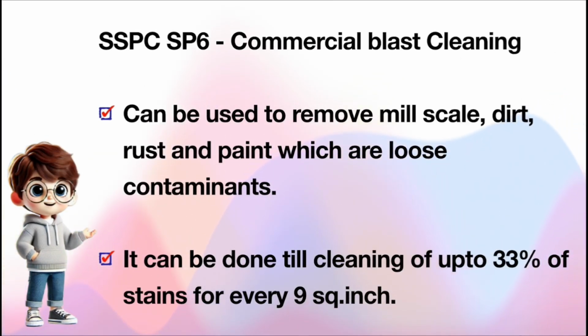Next, SSPC SP6, commercial blast cleaning. It can be used to remove mill scale, dirt, rust and paint which are loose contaminants. It prepares a steel surface by removing contaminants like oil, grease and rust, allowing up to 33% of every 9-inch square surface area to remain stained. Means after cleaning with SSPC SP6, on the entire surface of the steel, if you take anywhere a 9-inch square area, in that area stains should be a maximum of 33%.